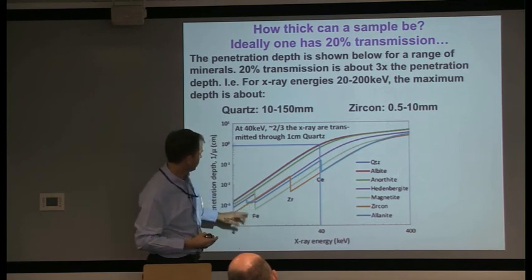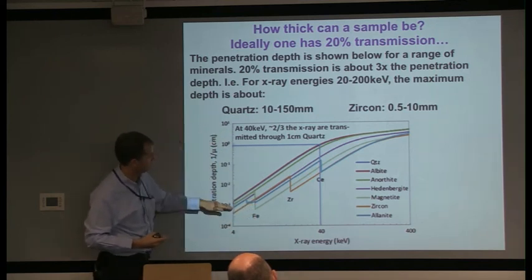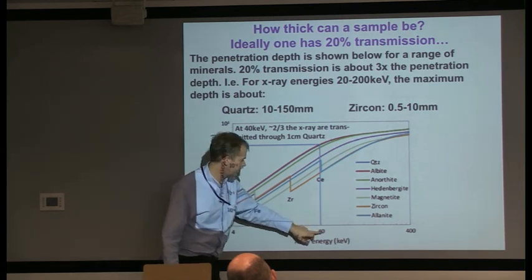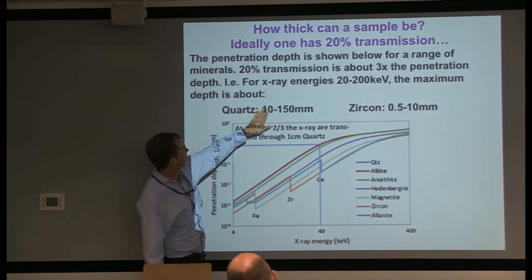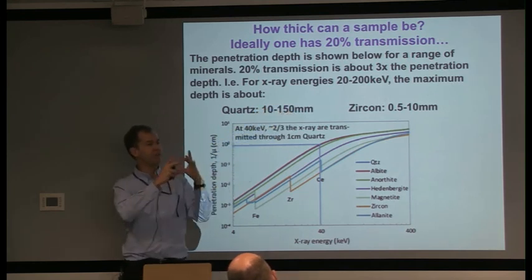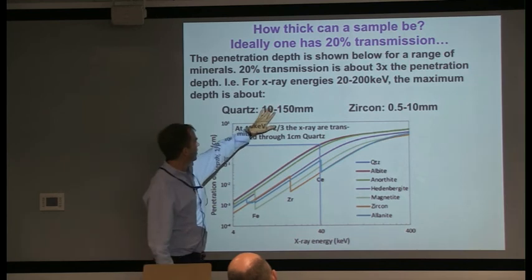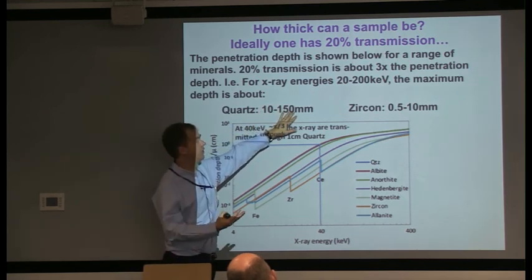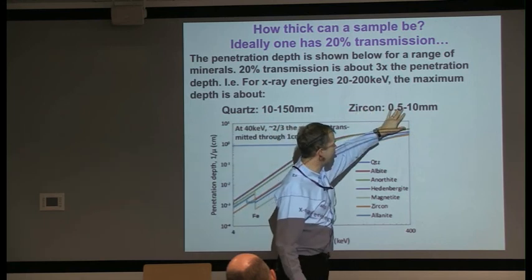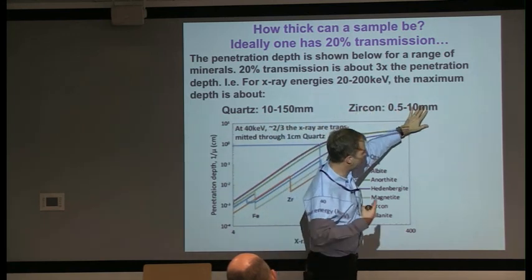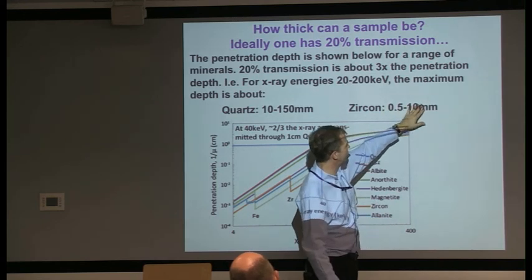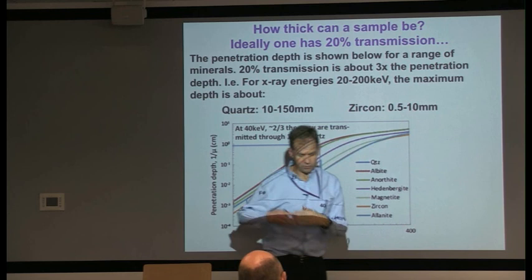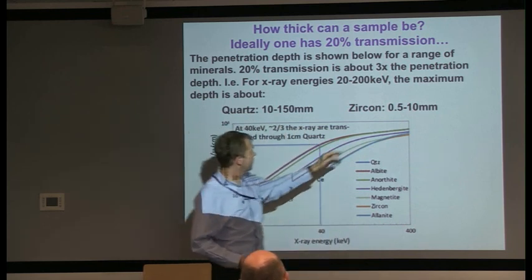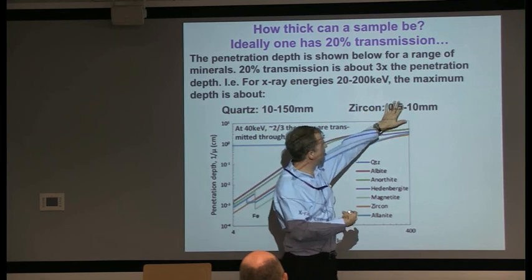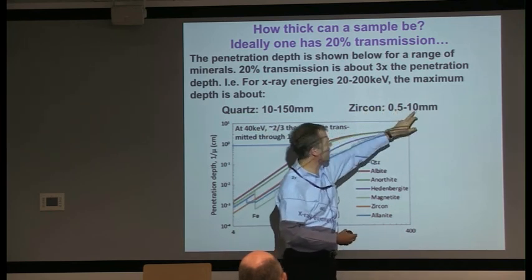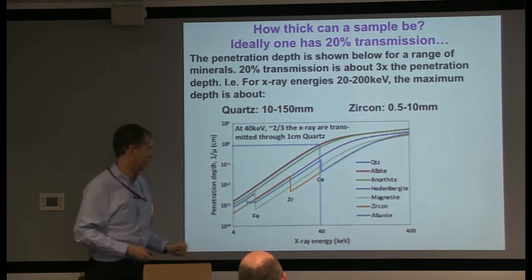If we look at how much penetration depth we can get, and take something like 40 keV - perfect if you have a soil sample of about this size - it goes through anything in that range and you get good resolution. If you've got zirconia, iron oxide, or something relatively high atomic number, or uranium in high concentration, the addition of density is linear but the attenuation goes up - you can now only go through about 10 millimeters at that same energy.